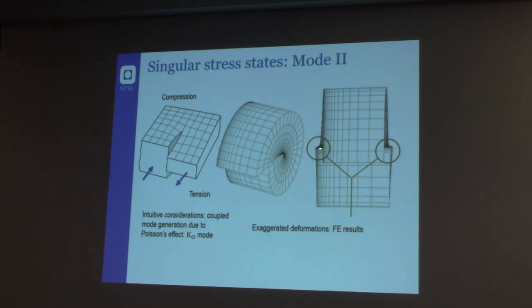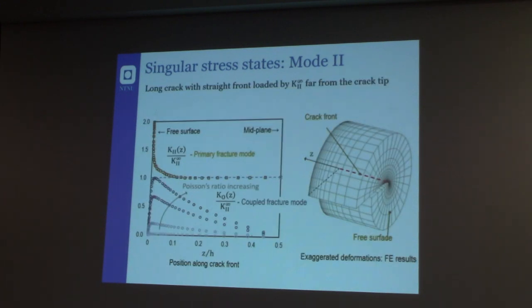So what is happening is that you have also a kind of Poisson's effect close to the free surface of the plate. Locally, what you are generating is a kind of coupled mode that is called mode O, the out-of-plane mode of fracture, which is not predicted by the two-dimensional fracture mechanics solution. Okay? And this KO, the stress intensity factor linked to the out-of-plane mode, is not negligible,